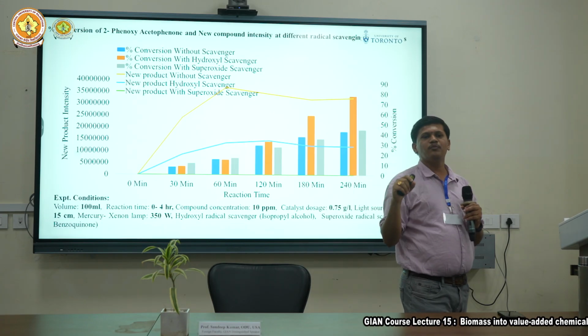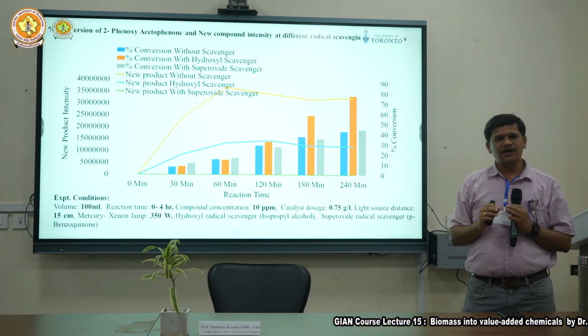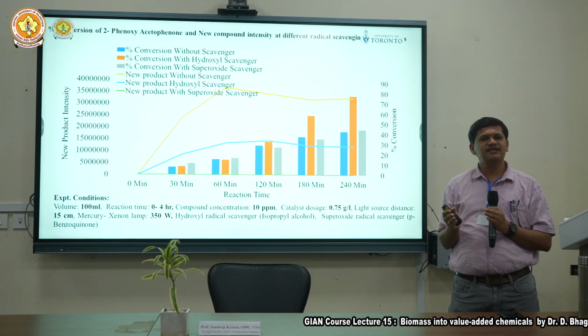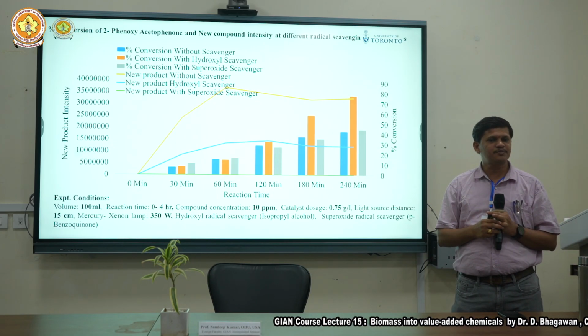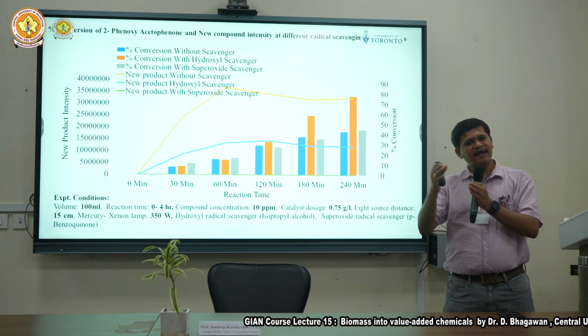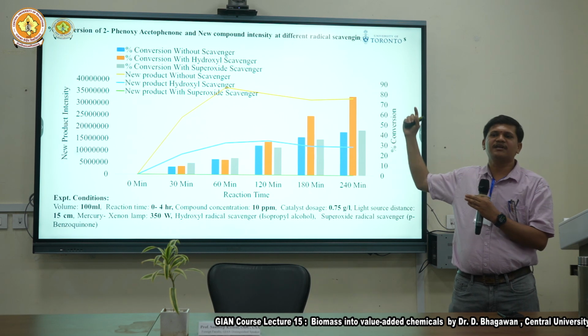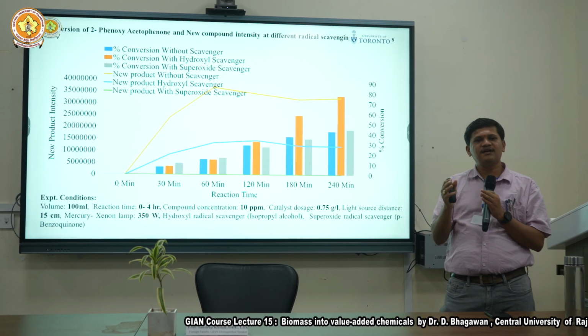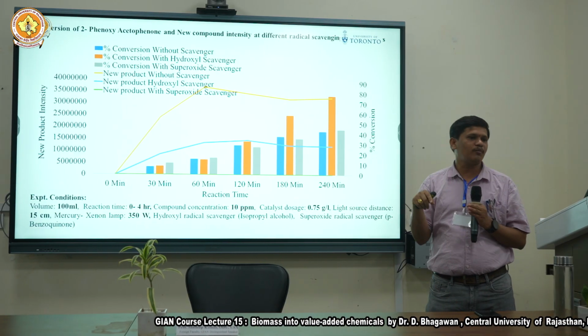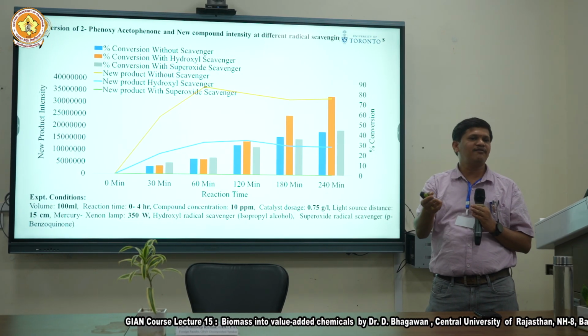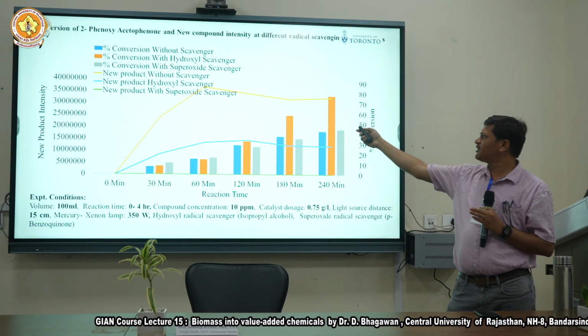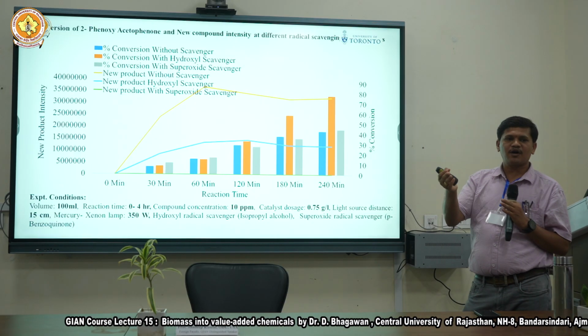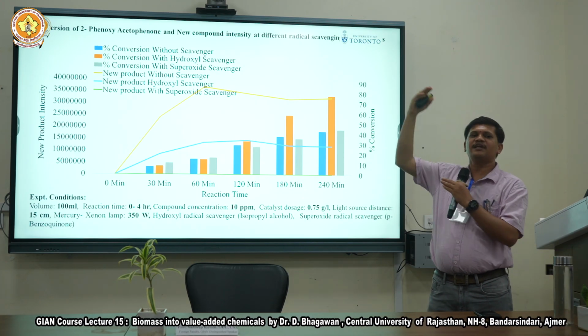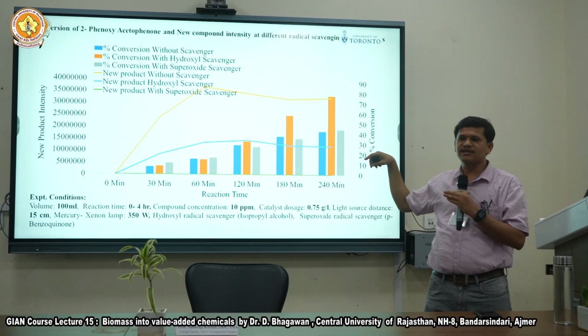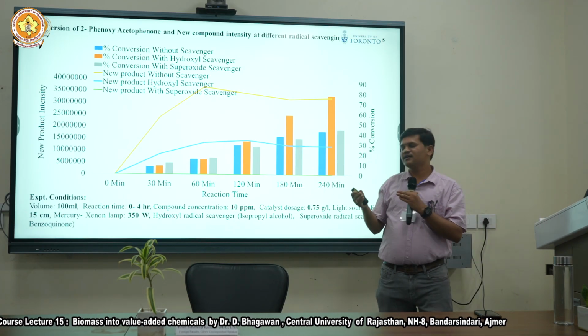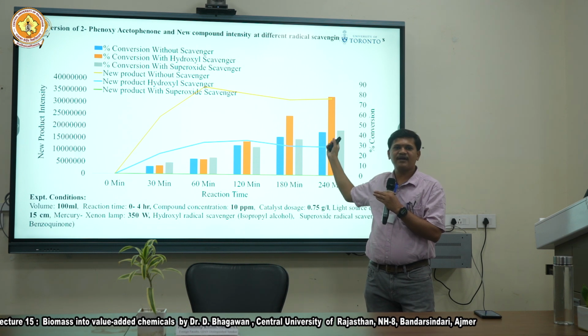Scavenger means the hydroxyl component is going to convert into water with the help of isopropyl alcohol. During the reaction we add some alcoholic species, which reacts with the hydroxyl species generated from the photocatalytic reaction, and because of that the OH radical becomes an H2O molecule. If it converts into H2O, then it is no more available for the reaction. So here we are controlling that. When we control that, the remaining species is superoxide, which is generated from O2 to superoxide. That superoxide is continuously generating, and because of that, new product formation has been identified with our reaction.